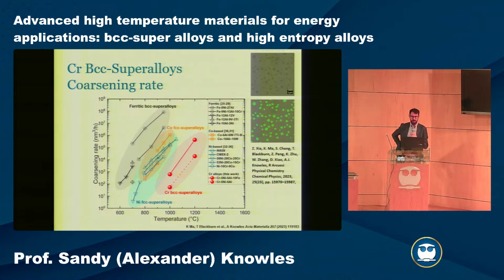One of the really interesting results within this new materials class of chromium BCC superalloys has been particularly the coarsening resistance. So we could anneal at a high temperature and particles will gradually get coarser. Ideally, in a high temperature material, you want things to be quite stable at your use temperature. If your material is changing in microstructure through time in service, you're going to change properties. So you really want something that's not going to change too much.